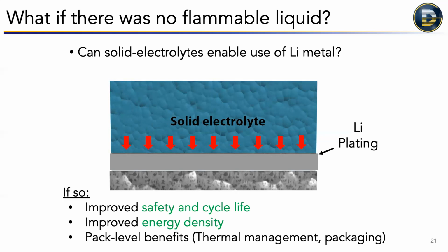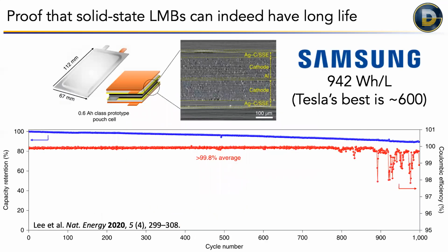So this sounds like pie in the sky stuff, but actually last year, Samsung put out this really foundational paper in the solid state battery field that proved that you can make a pretty large solid state battery that has significantly better energy density than even Tesla's best. And this is prototype scale, very frontier stuff. And they could cycle it almost 1,000 times with very little fade in capacity. And this is with a lithium metal electrode. So indeed, these solid state lithium metal batteries can have very long life. And just for context again, we'd be talking over 200,000 miles of life for an EV if it had a 300-mile range, roughly for 800 cycles. So this is a big deal.